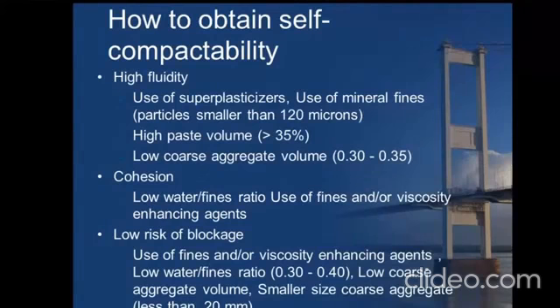For this paste volume, we have a lot of tests for paste. We have something called the Marsh cone test and the mini slump test. All these things are done in order to first tailor-make the paste combination. These are all very miniature equipment in the lab in order to customize your paste volume. So the paste volume plays a major role in self-compacting concrete. We need a high paste volume, and this can be achieved by using mineral admixtures like silica fume and fly ash.